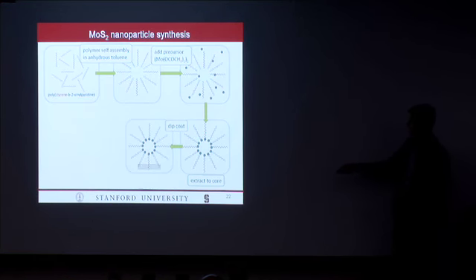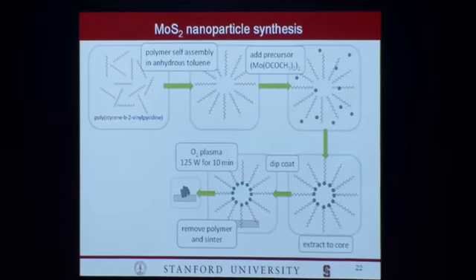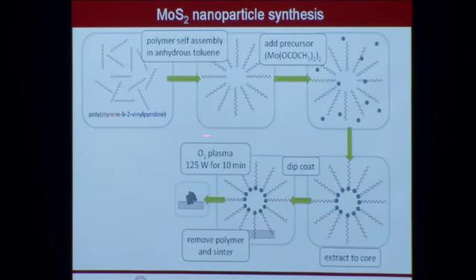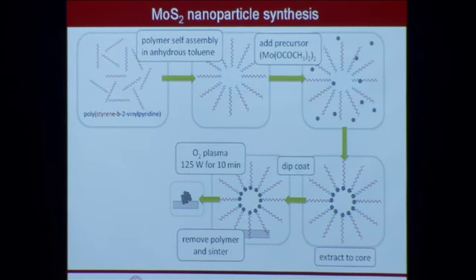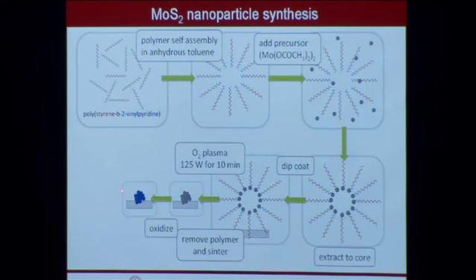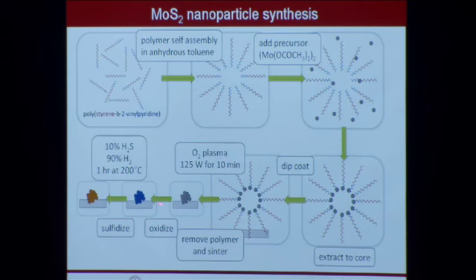Then we dip coat any substrate we want into that solution, and we pull out a flat surface with micelles sitting shoulder to shoulder, each micelle containing these metal cations. But then we need to get rid of the organic if we want to make a nanoparticle out of this, so we just oxidize this in an oxygen plasma, which is a fairly low temperature technique. We get rid of all this organic matter and we're left behind with this particle, which we can then further oxidize to ensure that we have a pure MoO3. And then from there, we can put these particles, supported onto any support of choice, in a furnace, 10% H2S, 90% H2, roughly 1 hour at 200 degrees C, and voila, you end up with MoS2 nanoparticles.